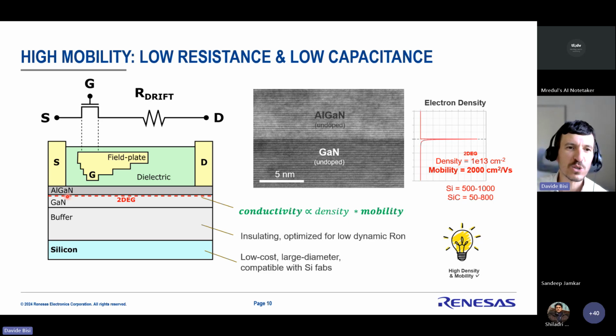Excellent. So, if you look at the active region, of course, we are all aware of it. We have an AlGaN layer on top of GaN, a very thin layer of AlGaN. And you can see here the interface on a TEM image, the very sharp interface, very pristine, high quality, atomic layer precision. And so this quality of interface, with the fact that both AlGaN and GaN are undoped, so there is no impurity doping, but the doping comes from polarization. As you know, we have a very good quality channel of electrons at this interface.